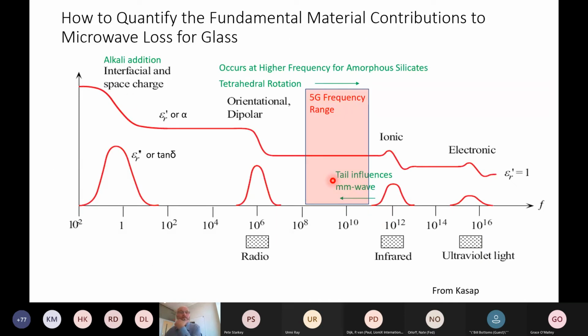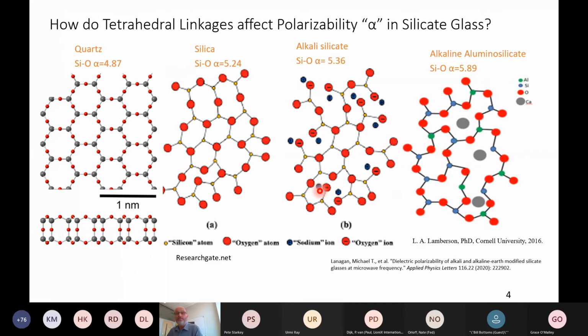And what we found was as we add these alkalis, we believe that we're changing the response of the glass. Normally, we don't think about dipolar response of oxides, but in glass, we do. And some of these tails and responses will come up into the 5G frequency range. And some of the ionic tails as well will come down into that range. And some of these loss peaks will spread out a little bit and really increase the loss quite a bit. We have studied this in detail.